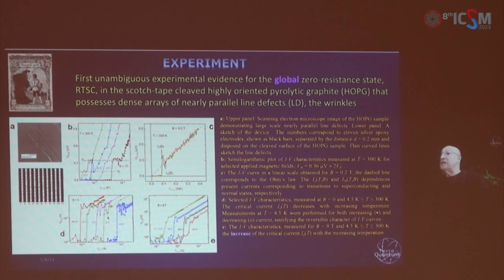And those are selected IV characteristics measured at zero magnetic field. And what we see is that the critical current decreases with increasing temperature, which is absolutely normal, this is what we expect. But what we immediately see when we repeat this measurement at finite, actually high, magnetic field is that now the critical current increases with increasing temperature, which was at first a little bit unusual and unexpected.